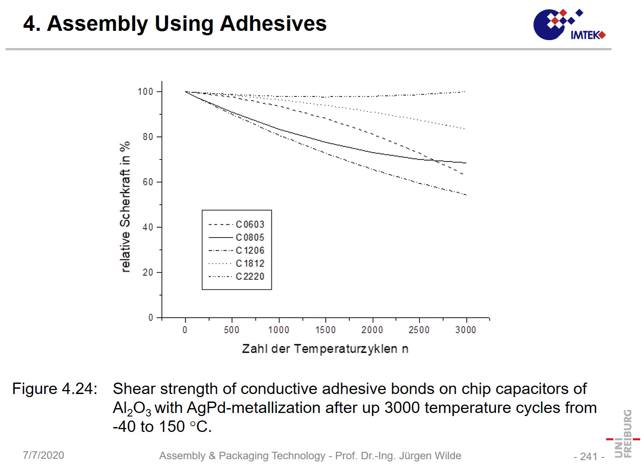Okay. Now, when you look at such conductive adhesive bonds, you are interested in reliability. For instance, in automotive applications, reliability is tested with 3,000 temperature cycles from -40 to 150 degrees centigrade. Now, when you take the shear strength and relate it to the starting value, you can see, depending on the device that you examine, that either the shear strength will be maintained constant, or in some cases it will decrease down to, let's say, 60%.